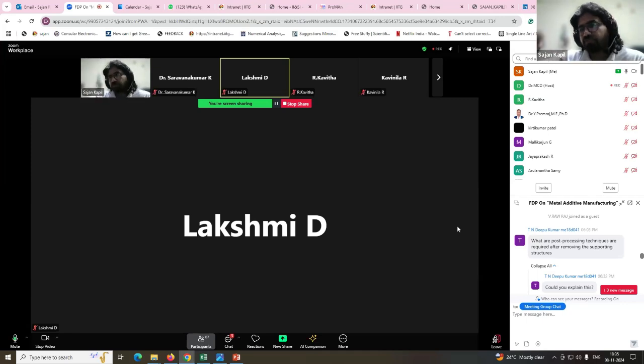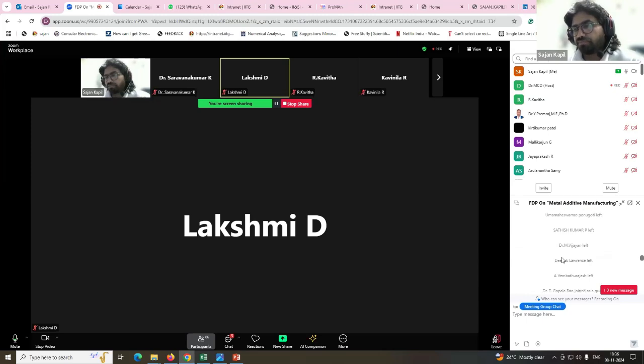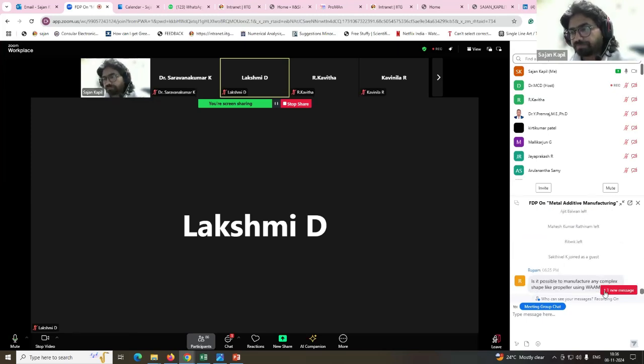One paper by Atul Singh Rajput you can read, in which he made the part by powder bed fusion, put it into an acid, and the surface got etched, reaching a desired level of surface roughness. Then he did magnetorheological fluid based machining. It's a polishing process, and reached one micron to 1 nanometer level. So fine, I hope you got it.